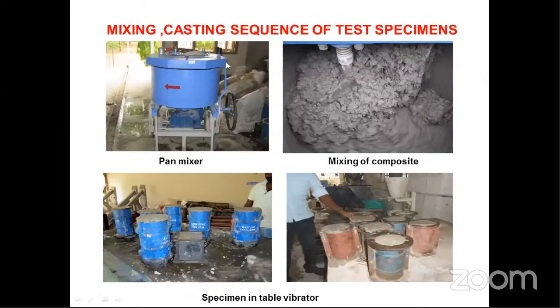And we compulsorily have to adopt this type of pan mixer for the production of FRC, because we are just adding the fiber, something like adding sand. So it should be properly distributed. The mixture should be homogeneous. In order to make the composite homogeneous, the fiber should be properly distributed throughout the mix, and the mixing process should also be done carefully. And table vibration is recommended in the literature, because we cannot adopt any internal vibration compaction like a needle vibrator, because we cannot place the vibrator inside the FRC.